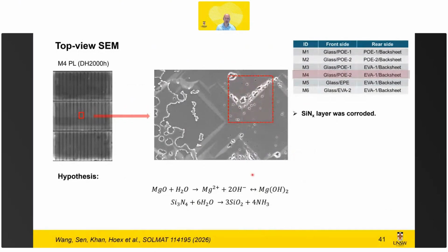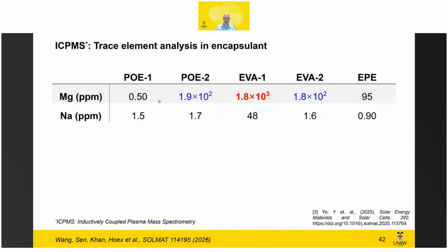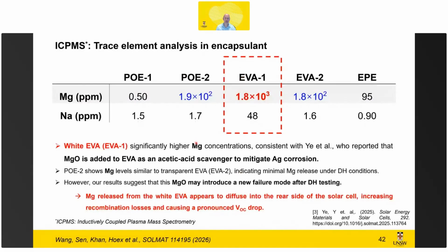But it's quite important to realize that there are some additives that can lead to corrosion of dielectrics, and that can lead to performance degradation. So in addition to interaction with the metallization, no part of the surface is safe from corrosion. And at the end we tested the magnesium content, and the worst performing EVA had the most magnesium. So there was a correlation. With the additional measurements we could make that causation. And of course in products now we use other acid scavengers than magnesium oxide.